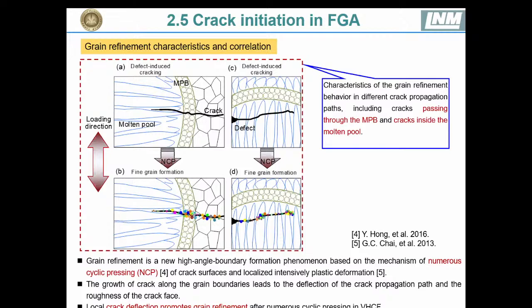refinement in very high cycle fatigue, the characteristic of this grain refinement is also studied, and also crack passing through the molten pool boundary, and also crack inside the molten pool boundary are also studied. And this grain refinement is a new high-angle boundary formation phenomenon based on the numerous cyclic pressing, and the growth of crack along grain boundary leads to the deflection of crack propagation path and roughness of the crack face. The local crack deflection promotes grain refinement through numerous cyclic pressing in very high cycle fatigue.